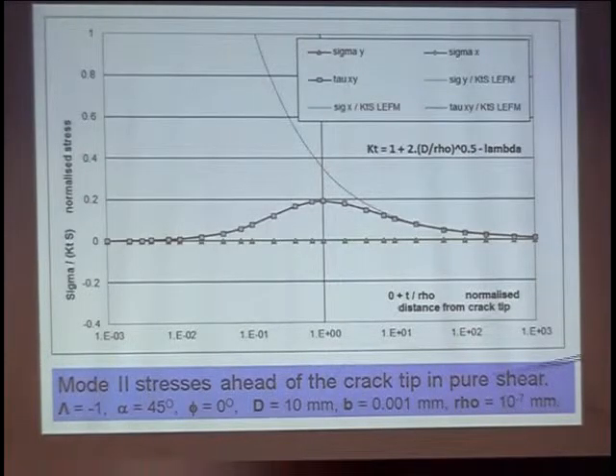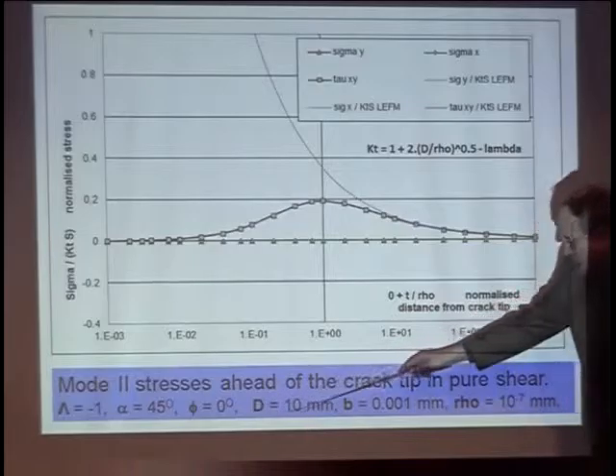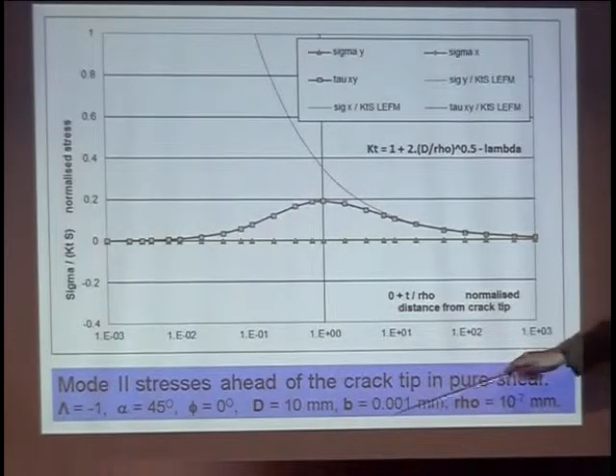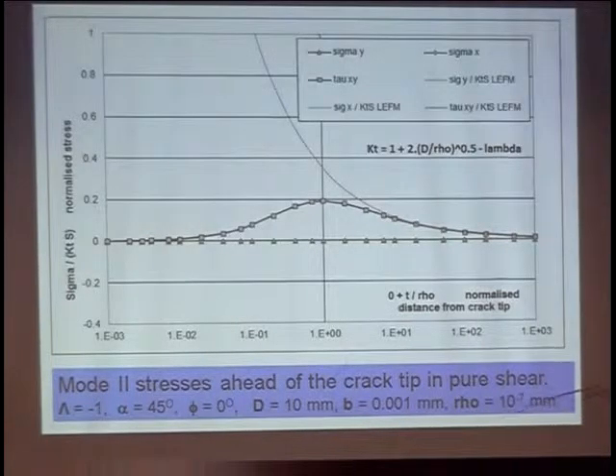I should practice a bit about dimensions and so on. I'll put down here my chosen crack shape. That's the length of the crack, or the half length of the ellipse, and the height. So it's a 10,000 to 1 ratio, so it's very crack-like. And in this case, the radius of curvature would be 10 to the minus 7 millimeters, or 1 angstrom.